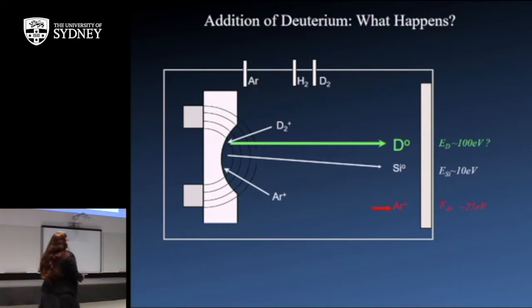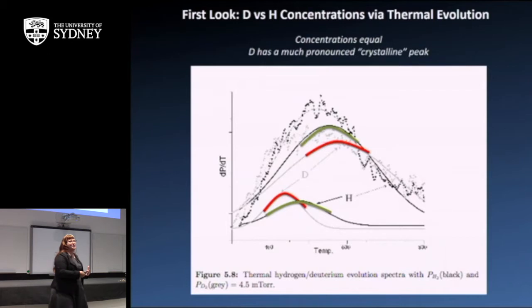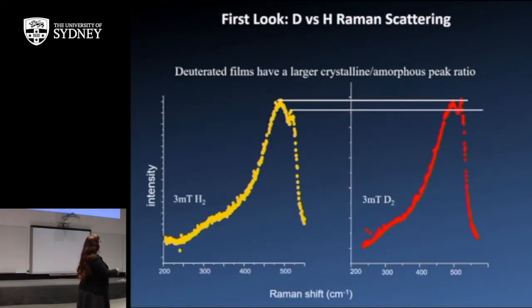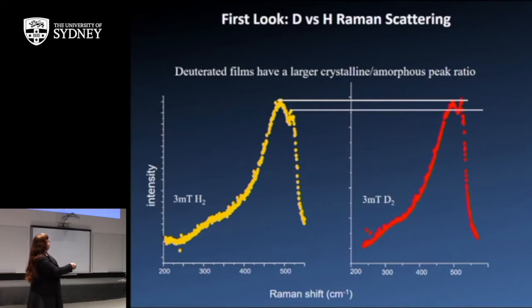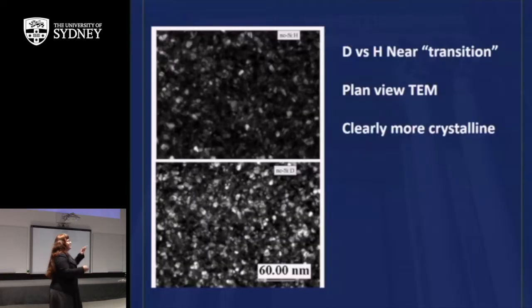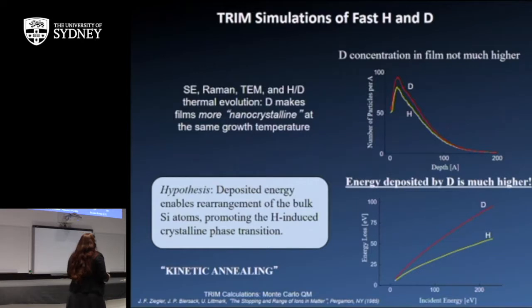So what we showed is that these films, and there's a lot of different ways to do it, were more crystalline. Even though they're still mostly amorphous and they have some crystalline parts in them, whenever you use deuterium, the films end up being more crystalline. For example, here's something called Raman scattering. Here's an amorphous peak and a crystalline peak, and the peak's higher for deuterium. So we measured this over and over again and proved that the films are far more crystalline when you use deuterium. And it turns out that it's exactly what you want to do.